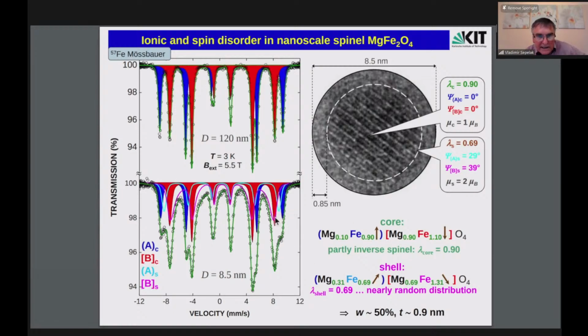Of course, from the intensity ratio of these 2 additional lines to the total spectral intensity, we can calculate the volume fraction of interfaces, about 50%, and knowing the size of nanoparticles, we can also calculate the thickness, about 0.9 nanometers, similar to previous cases.